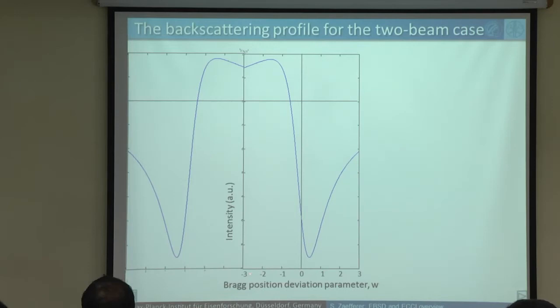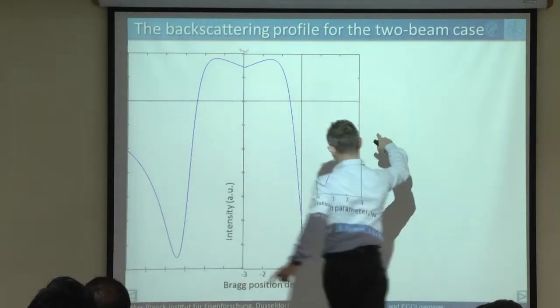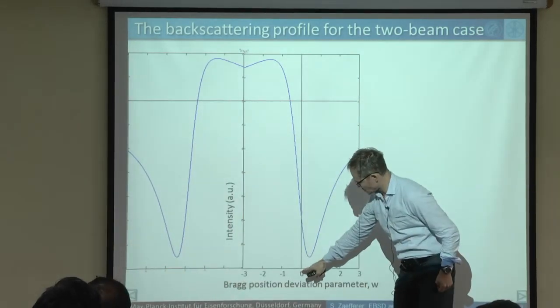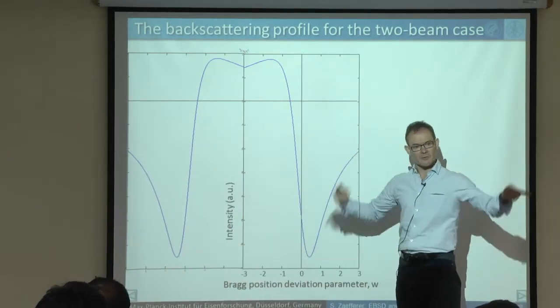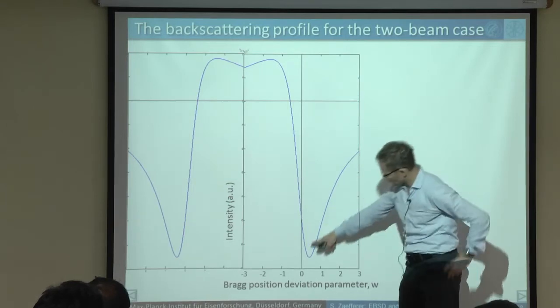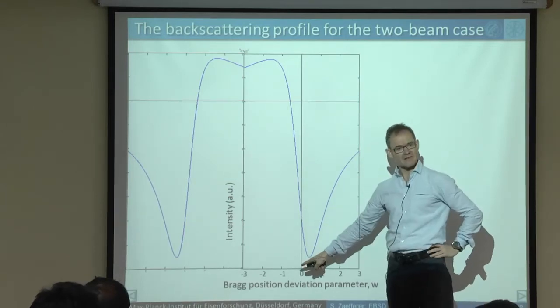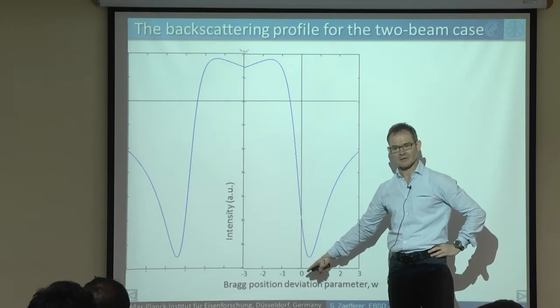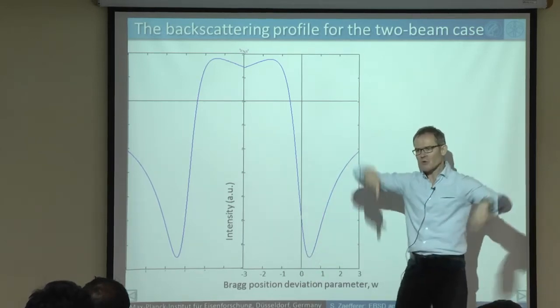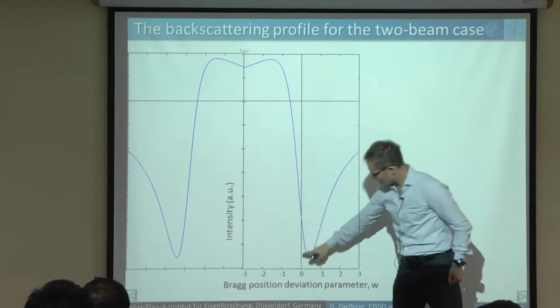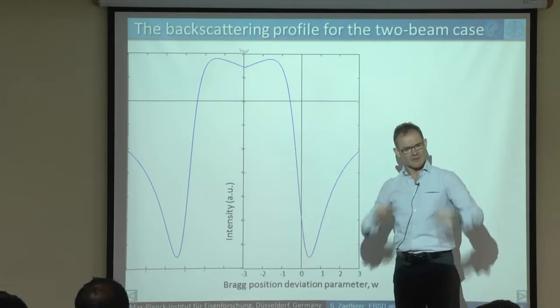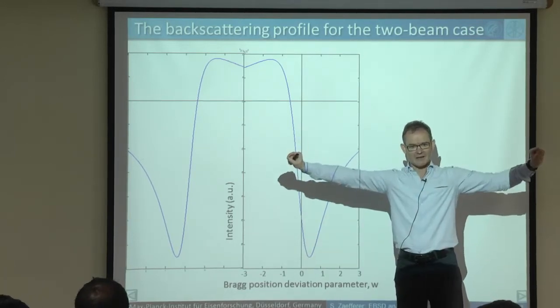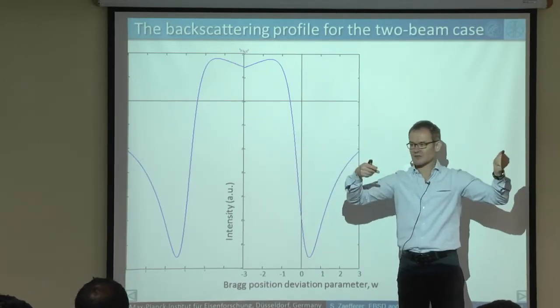Here is this deviation parameter W from 0 all the way to 3. And I calculate that, and I find that if we are very close to the Bragg condition, then this solution of the Schrödinger equation shows me that we are getting almost no intensity back. So there's almost no scattering getting through when we are almost precisely at the Bragg angle. That means we see a black line where we should intuitively think it's a bright line.